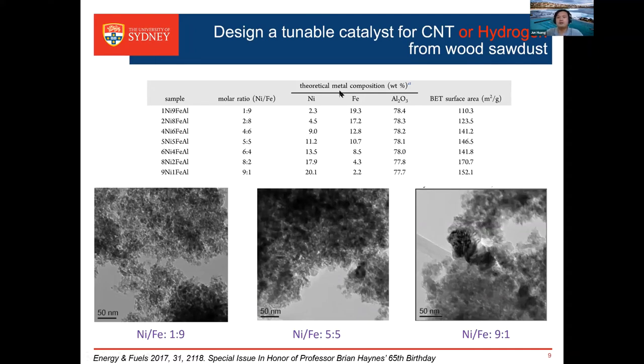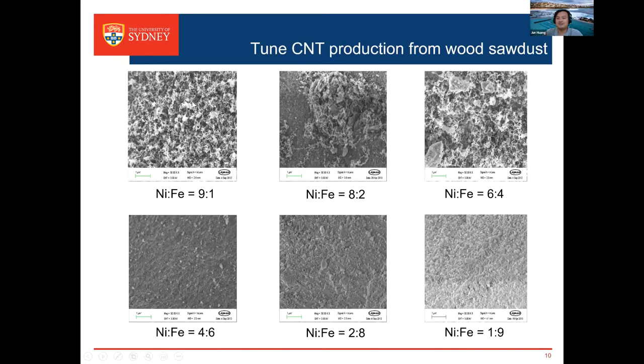And then we thought about whether it is possible to transfer this to some kind of waste. First, we tried biomass waste. Then we changed the catalyst to tune the production: majority hydrogen production with a small amount of carbon nanotubes, or a large amount of carbon nanotubes with a small amount of hydrogen, based on different catalyst chemical compositions. And we realized it. Based on this design, if the carbon nanotube price is good and the market prefers carbon nanotubes, we are able to generate a large amount of carbon nanotubes from biomass waste with a very small amount of hydrogen. However, if the hydrogen price is very good, we are able to generate mostly hydrogen-based gas with nearly no carbon nanotubes produced. So this allows us to switch the process to generate the preferred products.